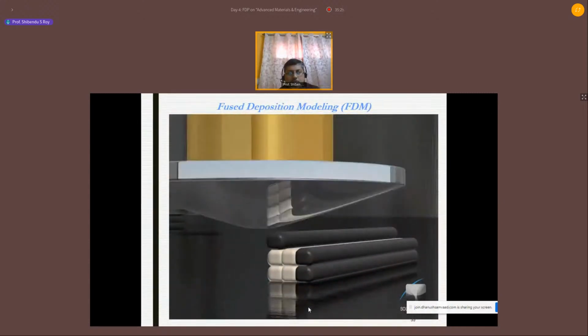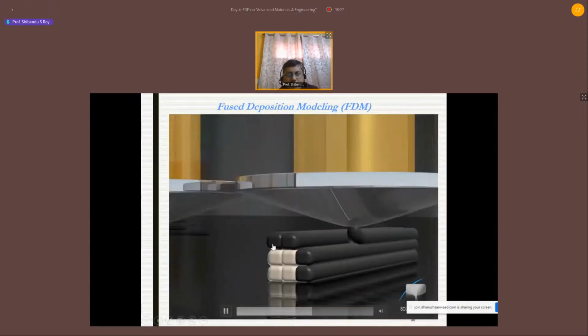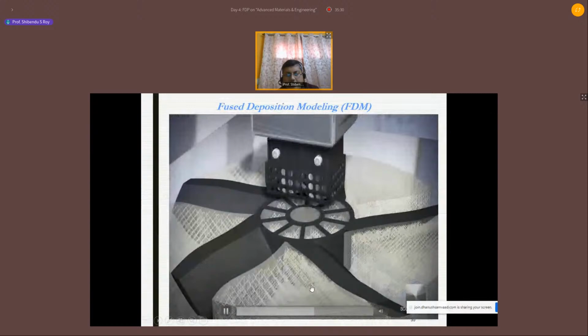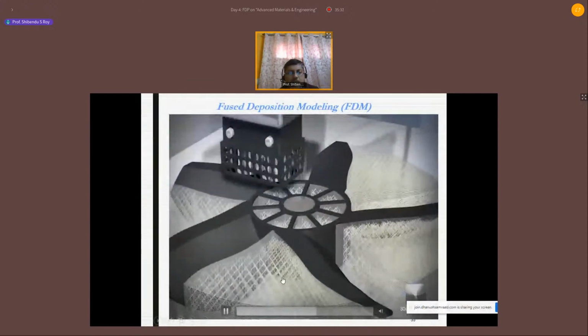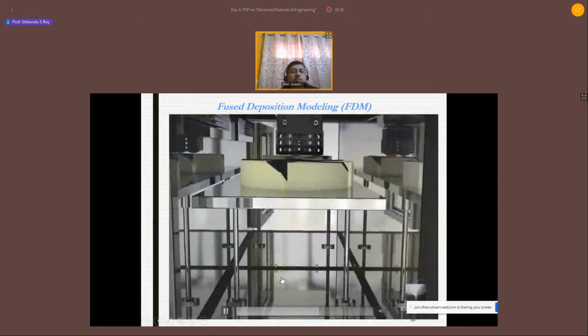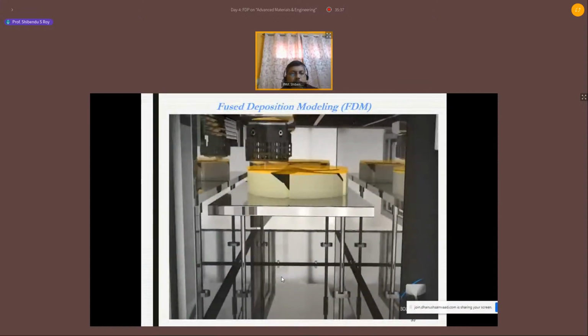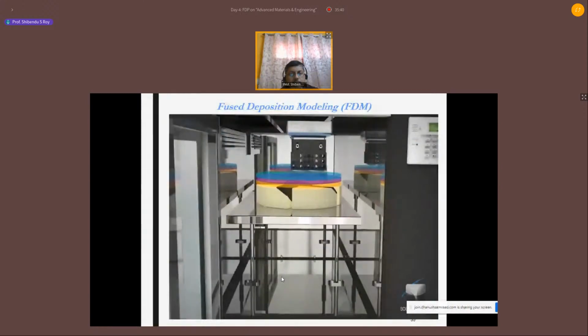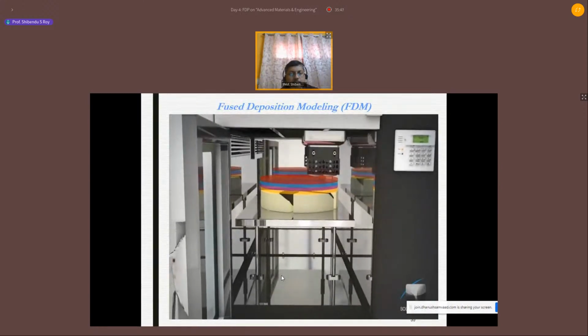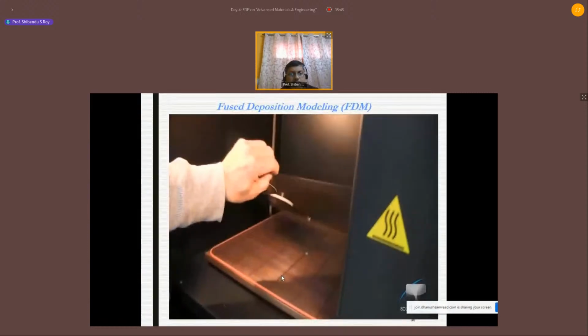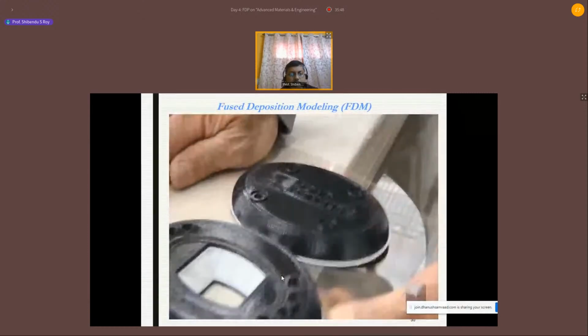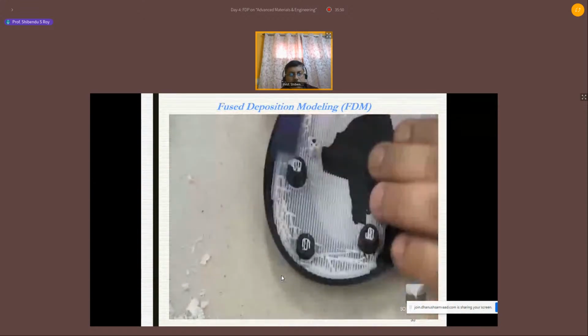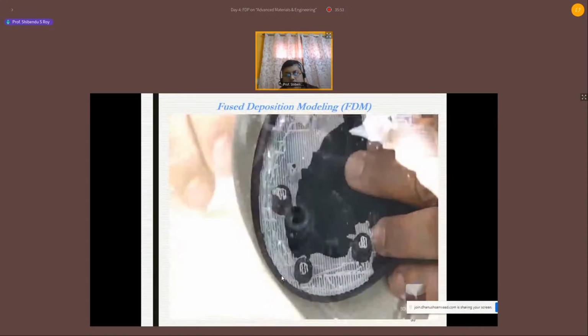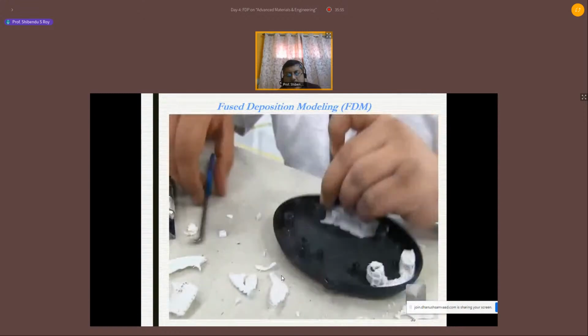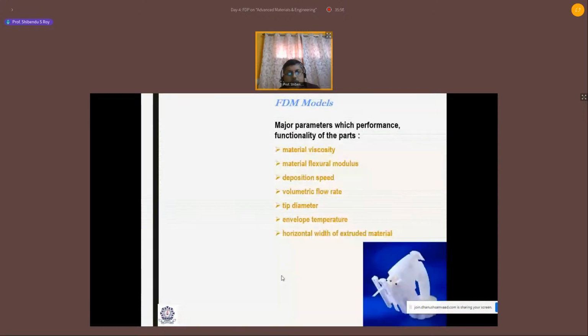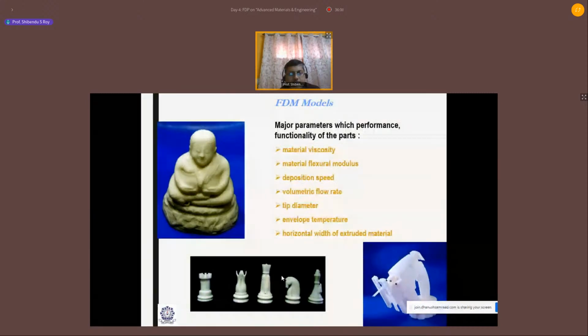So the white one is the support material. See, this is the overhang structure, the black one. So white support material is required. The extrusion nozzle continues to move in a horizontal XY plane while the build platform moves down, building the part layer by layer. The finished part is removed from the build platform and cleaned of its support material. Remove the support material for the overhang structure. So this kind of post-processing is required. So these are the different process parameters. This is the model developed.